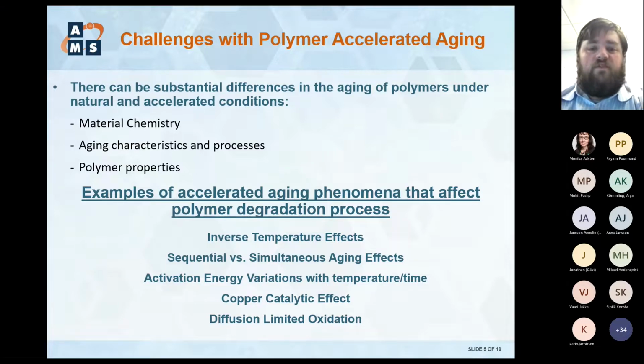So just a couple of examples of aging phenomena that might affect the polymer degradation process in materials. Inverse temperature effects, which are really prominent in semicrystalline materials subjected to aging under radiation conditions at lower temperatures. So we have a lot of chain scissioning reactions going on in that case, and they induce a lot of degradation in that regard. And then you also have to look into sequential versus simultaneous aging effects, which we're looking at in our project, but also looking at other work and trying to compare results from our project with people at the Nuclear Regulatory Commission of the United States. They have a project where they're doing simultaneous aging. We're doing sequential radiation, then thermal aging in one of our research efforts.